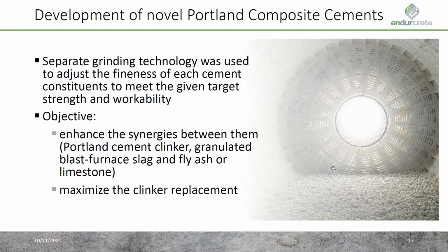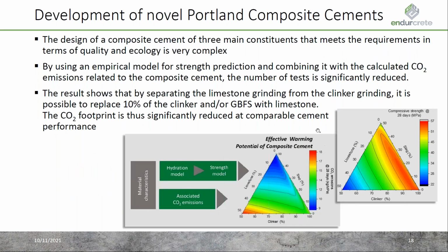And now where we are looking for lower clinker factors, we have to go in the direction of separate grinding, which means we have to grind every material with respect to the grindability and the reactivity to the best fineness to replace at the end the most of the clinker. If you work in such complex systems with 3 different materials in grindability and in reactivity, it will take a long time